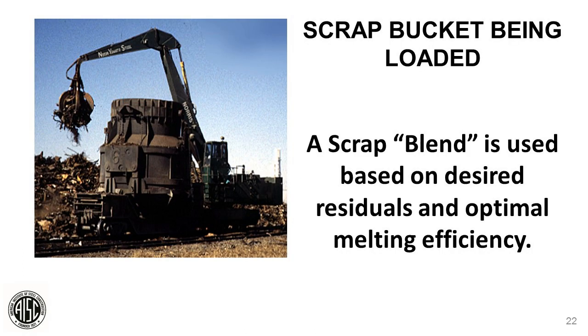So the scrap buckets are loaded by a crane on the outside, and we use a blend, basically a recipe. And in that recipe, we're trying to get the residuals as low as we need to make the product we're trying to make, and achieve the optimal melting efficiency.